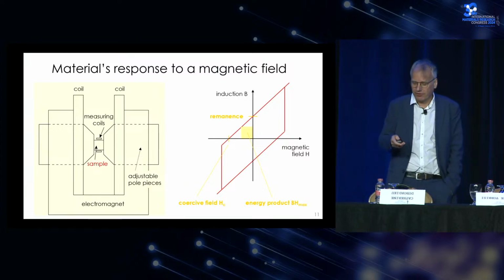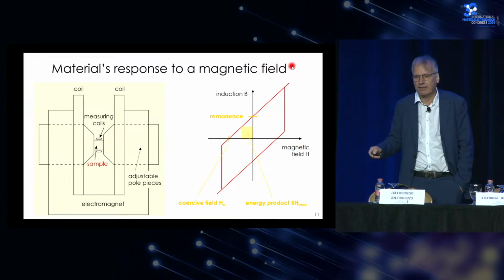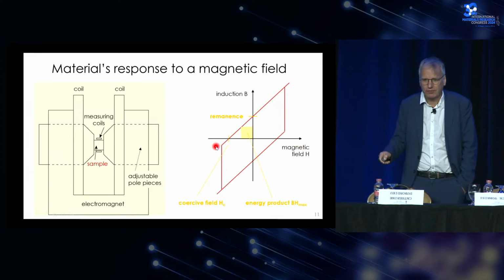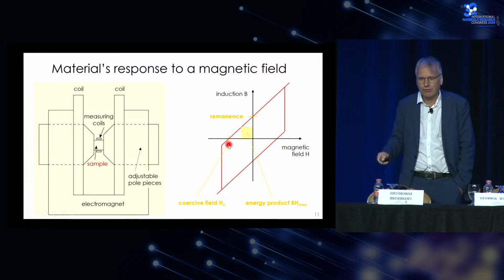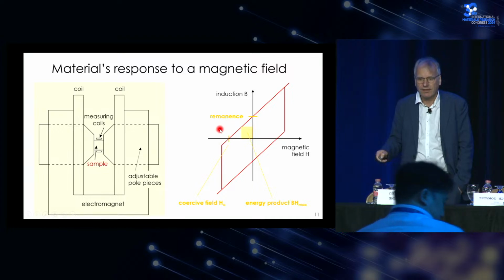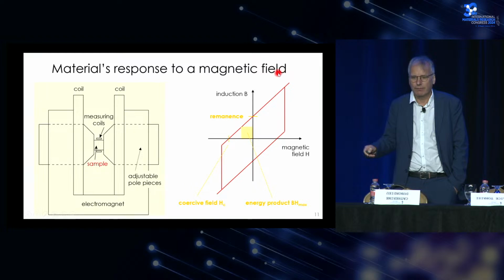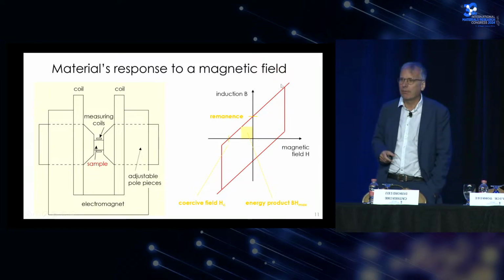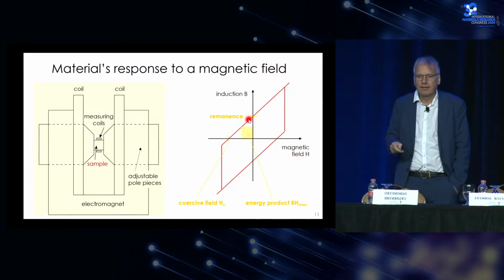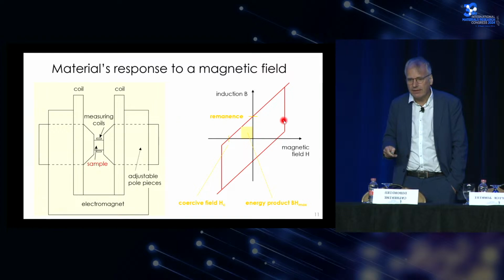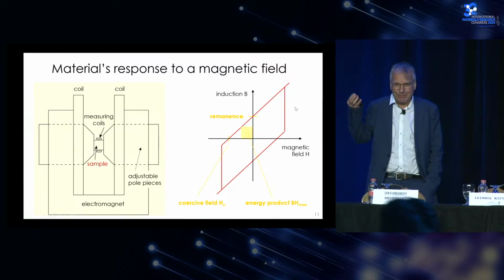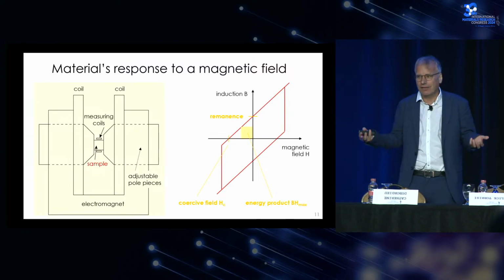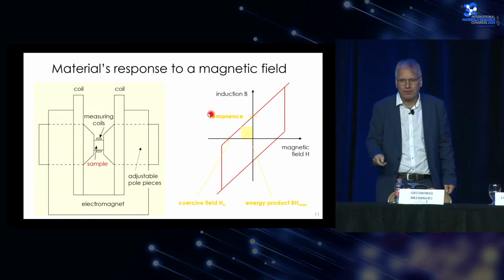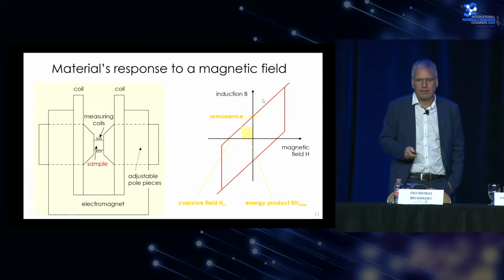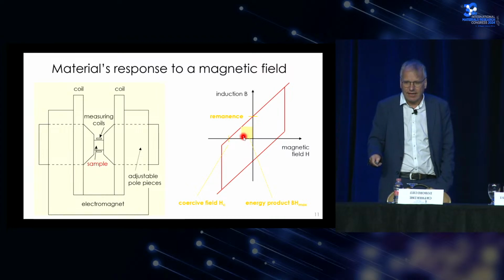We see that magnets have hysteresis, so if I apply a field, the magnetic flux increases. Then if we reduce the field, the flux goes down. At a certain point, we reach zero magnetic flux. This is the so-called coercive field. Then we go down and reverse the field, and we have the typical hysteresis loop of a permanent magnet. In addition to the coercive field, two other important properties are the remanent magnetization, which is the magnetic flux that remains if there is no field applied to the magnet. This is an important quantity because it is related to the field that is created by the magnet itself. And then the largest rectangle I can put below this curve is the energy product.